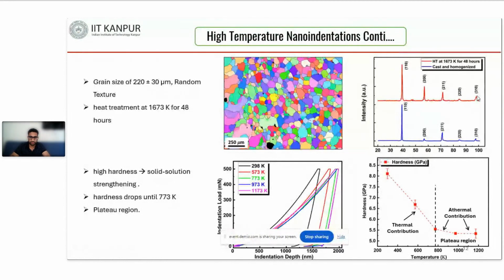Then we jump to the nanoindentation testing. We did nanoindentation tests at 298 Kelvin, 573 Kelvin, 773, 973, and 1173 Kelvin.